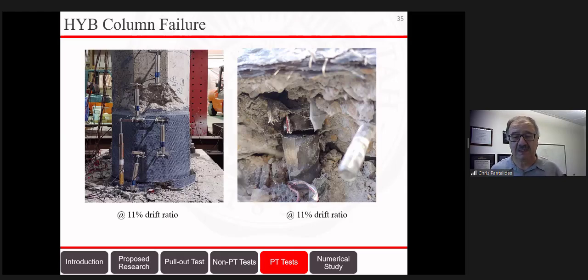And then at 10%, the carbon wrap fractured. And we can see it ruptured about a 2-inch strip, just came off. But of course, at 11%, we saw that one of the mild steel bars fractured. So 11% is an unbelievably high drift ratio. I need to stress that. And the performance, as you saw up to that point, was excellent.